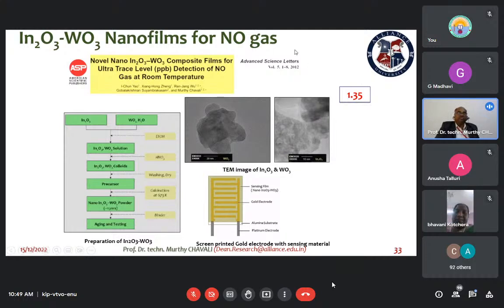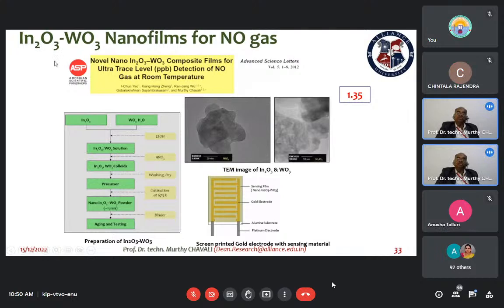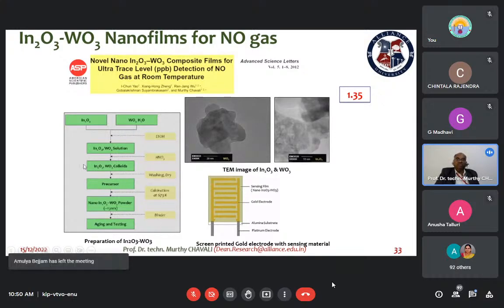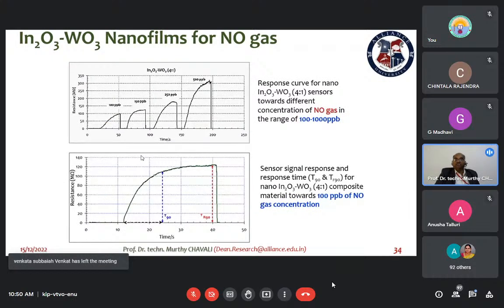But initially we failed in developing a NO gas sensor in a liquid stream, like a gas and liquid matrix. In the initial studies, we thought of developing this in a gas matrix using indium oxide, where the temperature was very high. To reduce this, we tried different ratios of indium oxide to tungsten oxide, and finally we prevailed by preparing an indium oxide tungsten oxide sensor at a 4:1 ratio to detect NO gas in a gas matrix, so that we will be able to have the dynamics and interference.